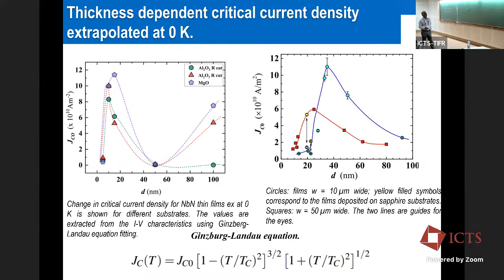Now, a very important parameter in there is the critical current density. A very nice phenomenon we can see there, because the quantum phenomena are very much prominent in here. So as you are decreasing the thickness, right, your current density increases, and there is a crossover point. We call it a three-dimensional to two-dimensional, two-dimensional to three-dimensional crossover, and your current density is again increasing in here. While in the case of niobium, your current density is continuously decreasing after a certain thickness.